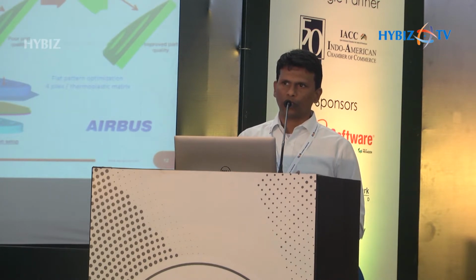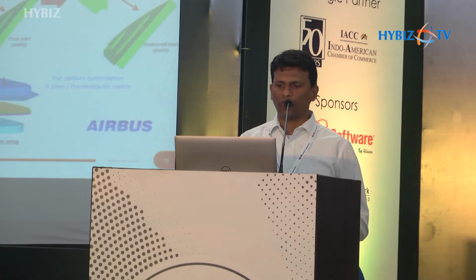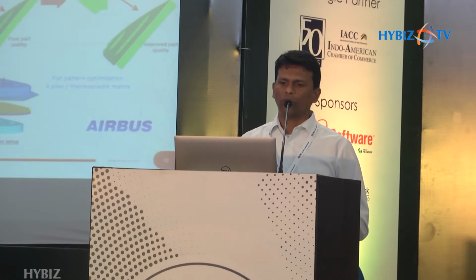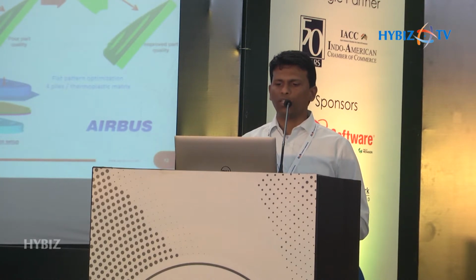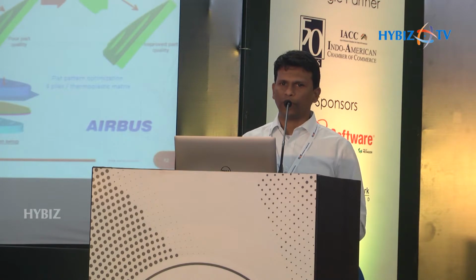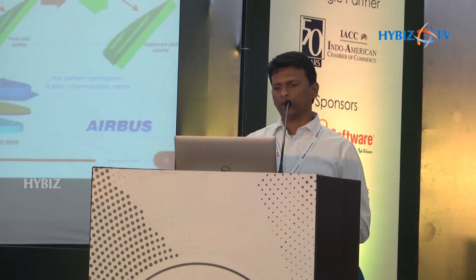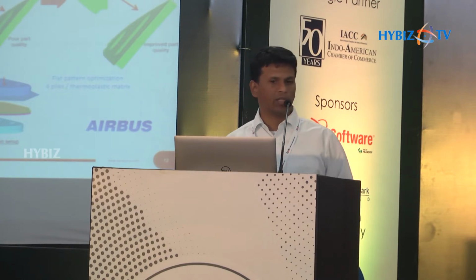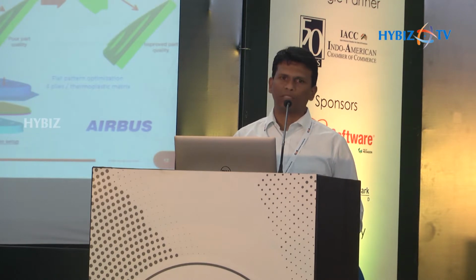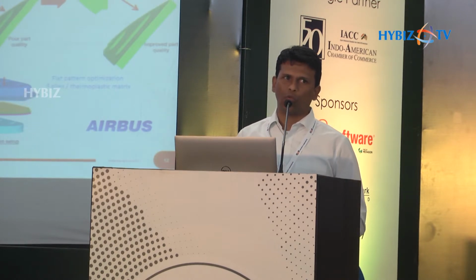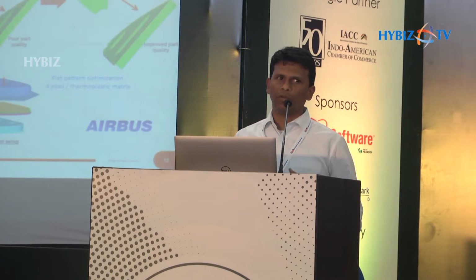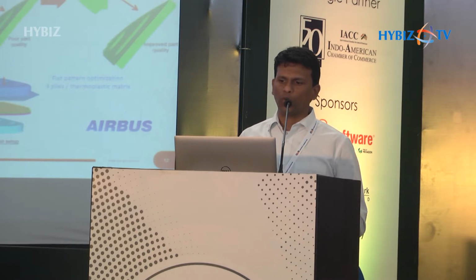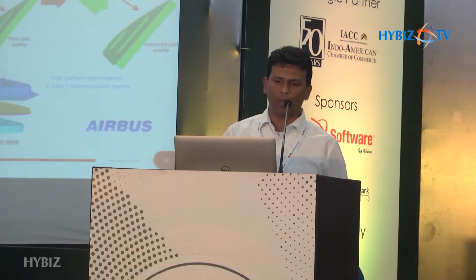One such tool was basically the flat pattern, or the outline of the blank that probably has to be used to reduce the amount of defect or the poor quality that is coming out. So we were initially able to successfully simulate the 4 plies flat pattern, and then we understood that there is a large amount of wrinkles that is coming on the component, and then the optimization solver was launched behind, and then it was able to give us an optimized output flat pattern, which was used for a defect-free component manufacturing.